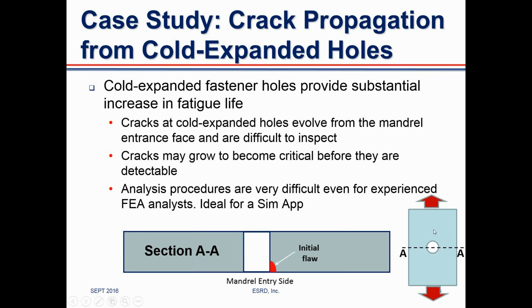Here you have a cross-section of a plate where the hole is located that has been cold worked, and what we have been observing in practice is that cracks at cold expanded holes evolve from the mandrel entrance side. And that is the area which is more difficult to detect. So the mandrel enters on this side and exits on the other, and if the crack has the chance to form, it will happen at the entrance side. What happens typically is the outside surface is the one that is exposed, let's say the skin of an aircraft, and the inside is not easy to access. So cracks may grow and become critical before they are detectable.